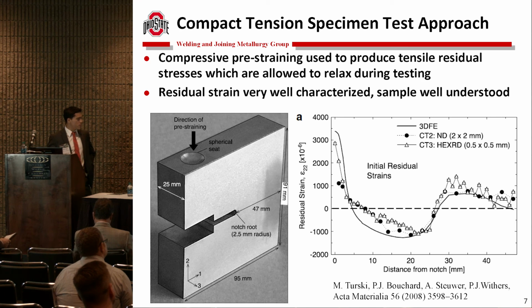So what you do is you take a standard compact tension sample and pre-strain it in compression, and then you yield a little bit of material behind the notch root, and then you unload the sample. So now the part which you yielded is in a tensile residual stress. And so you simply put this sample in the furnace, unload it, and let that stress relax, and you arrive at an accelerated creep test.